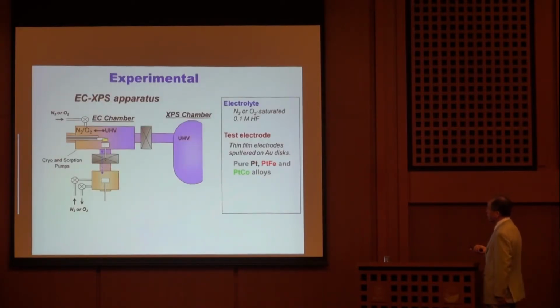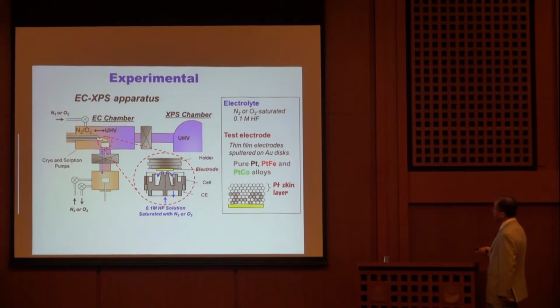And we made an electrochemical chamber attached to the XPS system. We use 0.1 molar hydrofluoric acid HF solution, with dissolved nitrogen or oxygen, and test electrodes were prepared by sputtering pure platinum or platinum iron or platinum cobalt, and pre-treated the surface in an electrolyte to form the stable platinum skin layer.